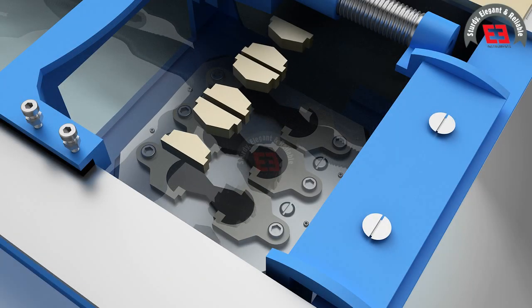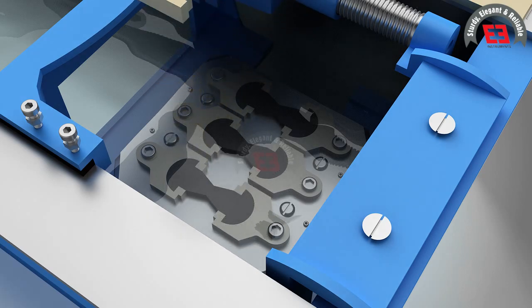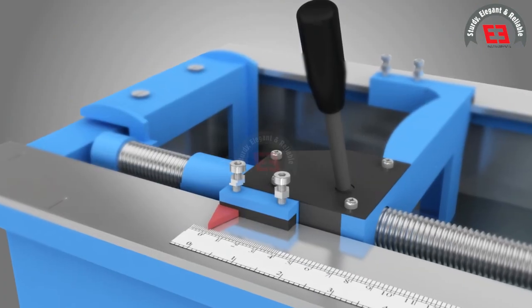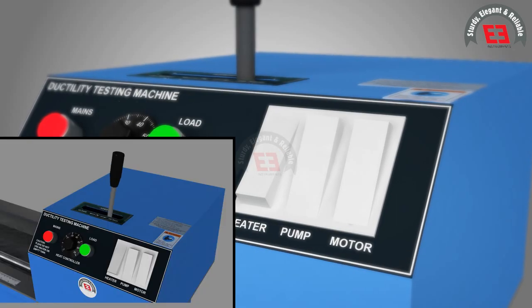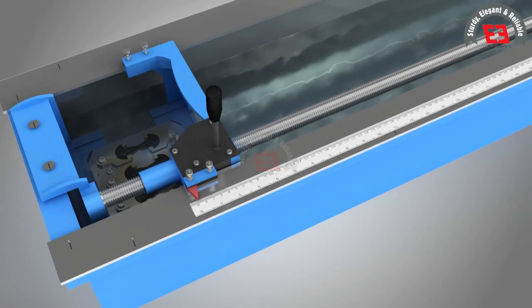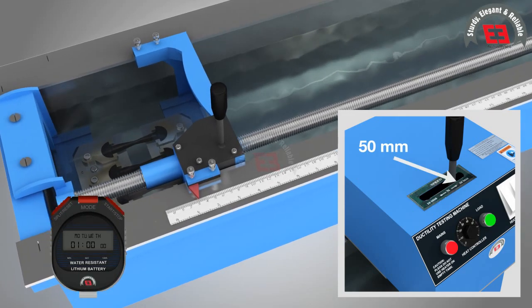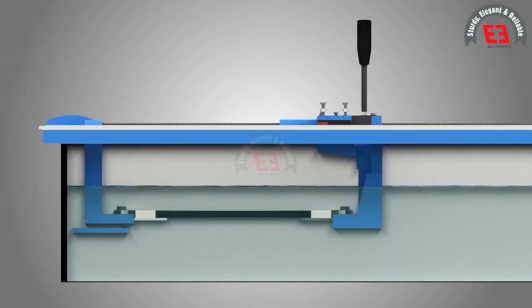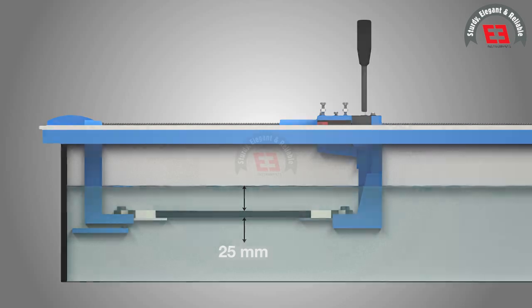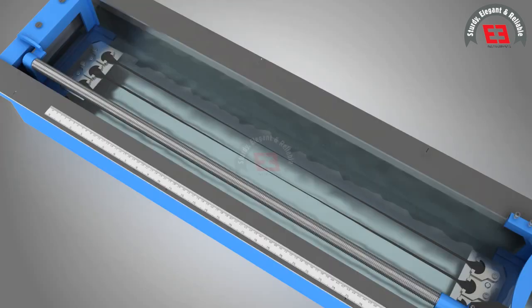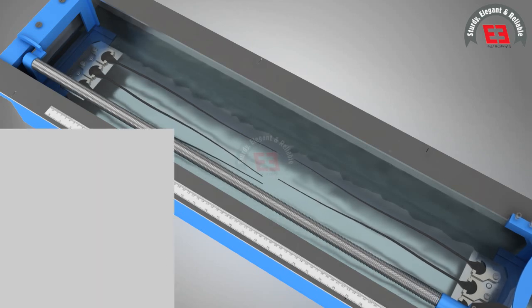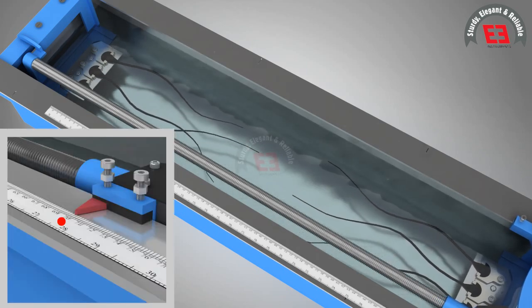The side pieces of the molds are now removed. The pointer is set to zero and the machine is started, and the two clips are pulled apart at the rate of 50 mm per minute. The sample is immersed in water above and below by at least 25 mm while performing the test. The distance at which the bitumen thread of each specimen ruptures is recorded as the ductility value in cm.